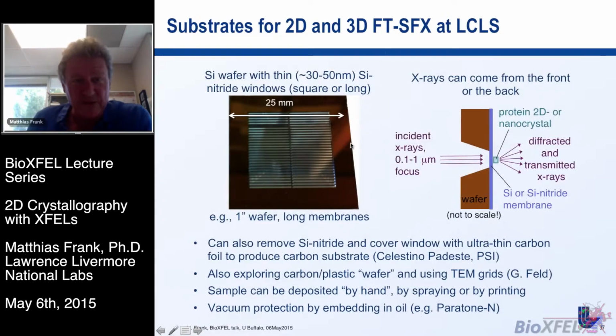We've also explored wafers with thin and long windows. Instead of having little square windows, we have these elongated membranes. They're also 30 or 50 nanometers thick. They're about 1 centimeter long, 200 micrometers wide. And what you can do with a long membrane is you can have the X-ray free electron laser like LCLS pulse at a fixed rate, let's say 10 hertz. And then you can continually move that membrane through the X-ray beam, and you get about 100 shots or so into 1 centimeter, if you space them out by 100 micrometers. So this way you can speed up the data acquisition.